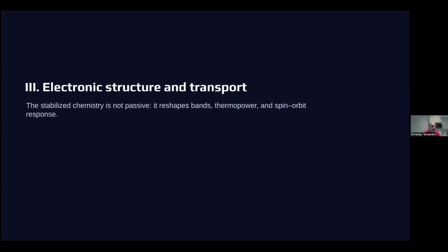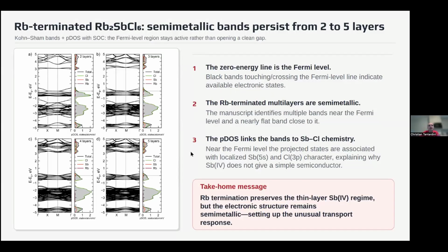So we now have an interesting compound, the B layer, thin, that can be electronically interesting, and we look at the electronic transport. Specifically, as I mentioned before, we chose the rubidium terminated one specifically for this kind of electronic structure close to the Fermi level.